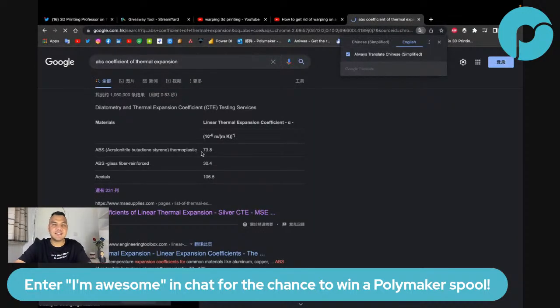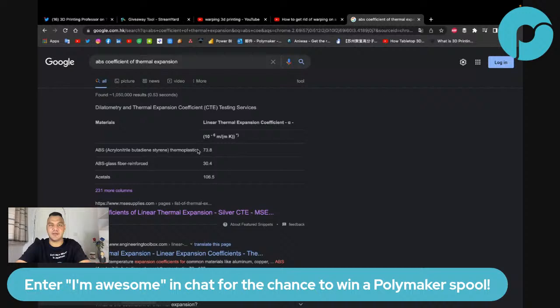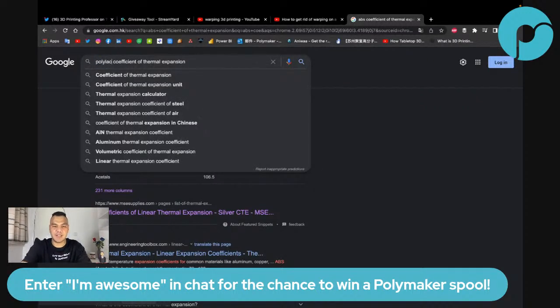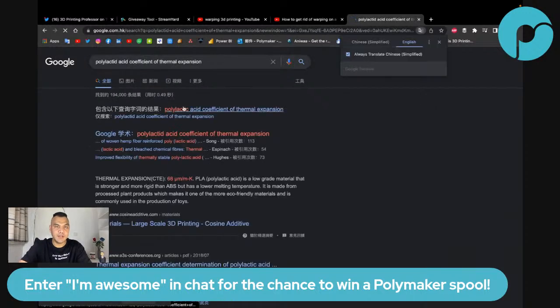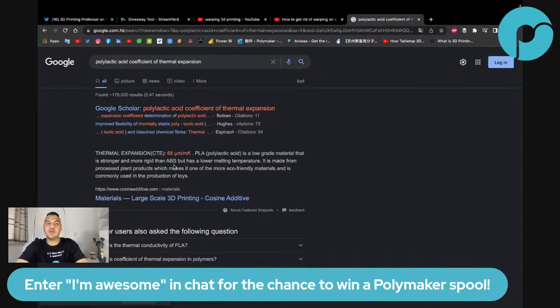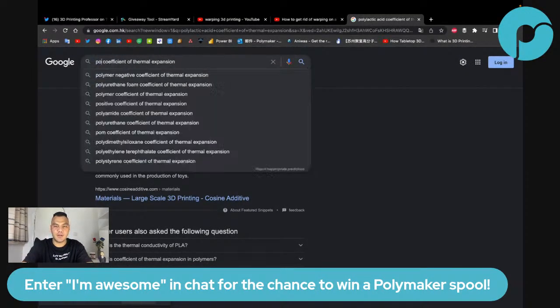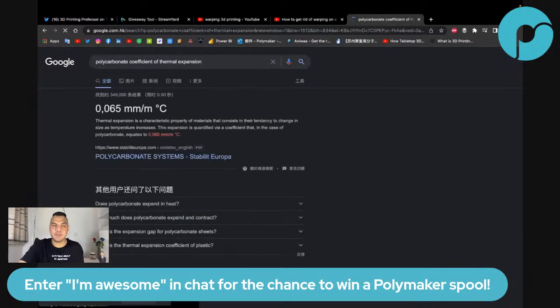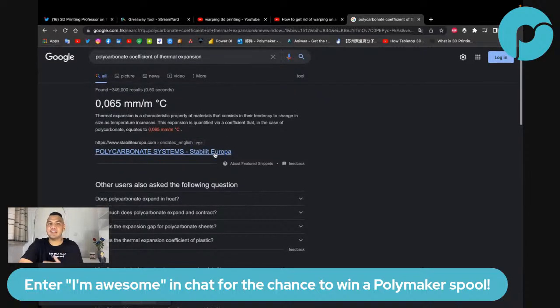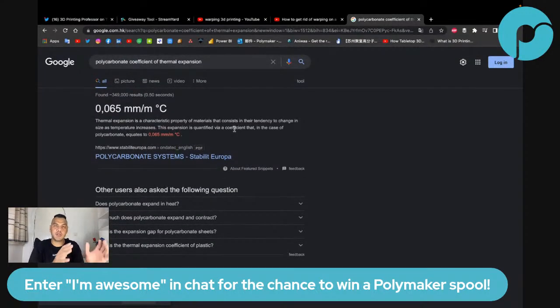ABS coefficient, I think I looked for that already. Thermal expansion, so ABS 73, okay, let's say 80, 73.8. Okay, PLA, polylactic acid, PLA 68. So you have 73 for ABS, 68 for PLA. So PLA, lower coefficient of thermal expansion, no problem. And now PC, polycarbonate, has the same or similar. Okay, also 65, so it's the same as PLA. So now the question for the team that is thinking about this: why is polycarbonate warping way more than PLA if they have the same coefficient of thermal expansion? That's the first argument.